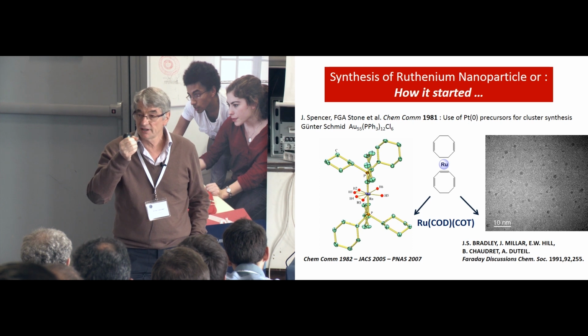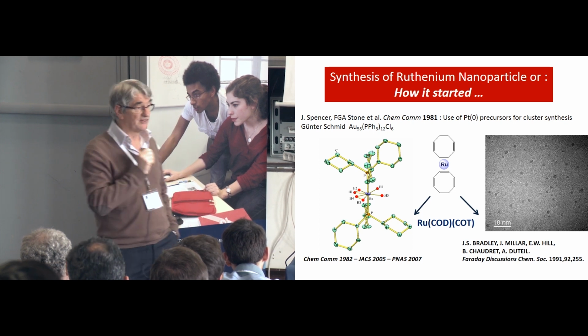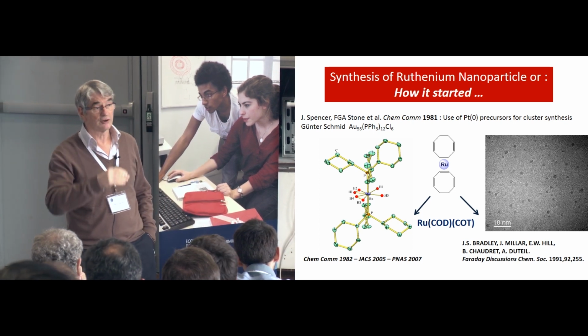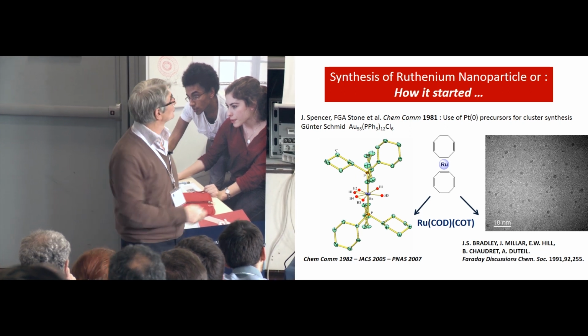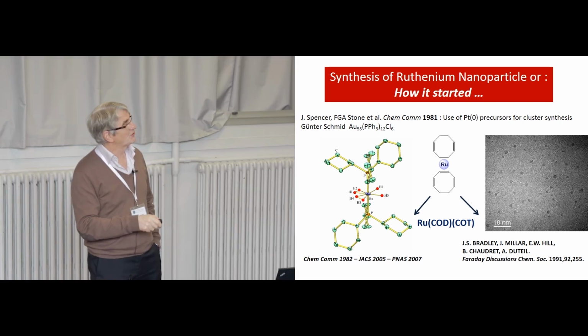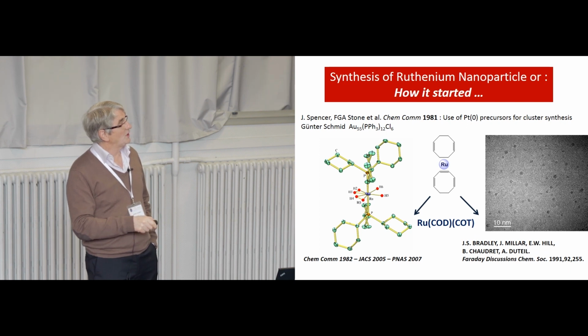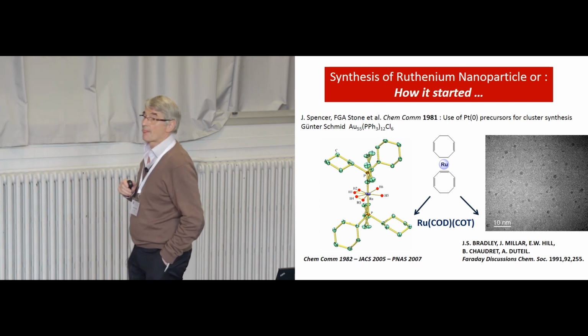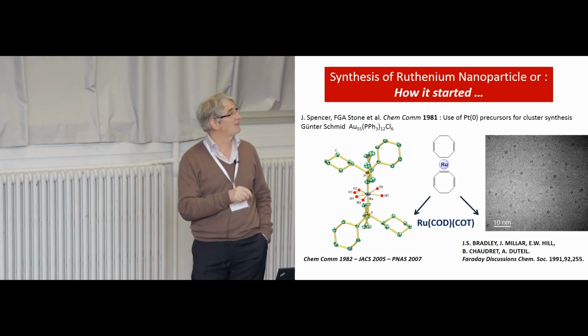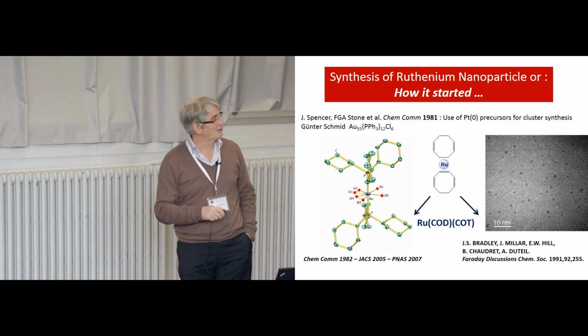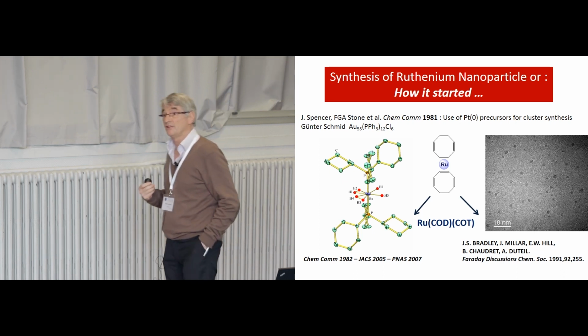This precursor, you just feed it a little bit with hydrogen at room temperature or below, and it decomposes nicely. With some ligands, we got this compound, ruthenium dihydride bis-dihydrogen. And that kept us busy for 25 years.